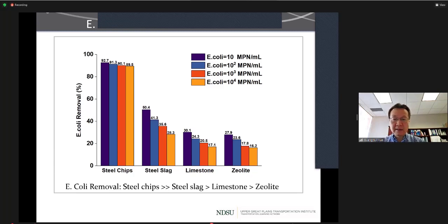And we found that the influent concentration had a larger impact on steel slag, limestone, and zeolite. And also, we found a similar removal efficiency order as in the kinetic study. So overall, based on the E. coli removal at different concentrations, we conclude that steel chips are much more efficient than steel slag, which is more efficient than limestone and zeolite.